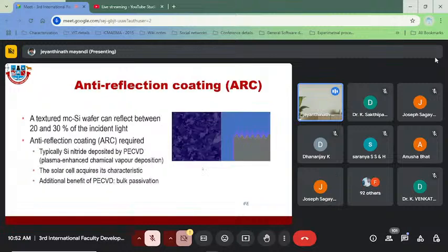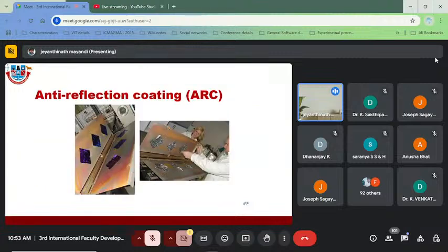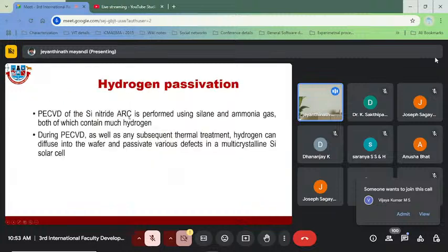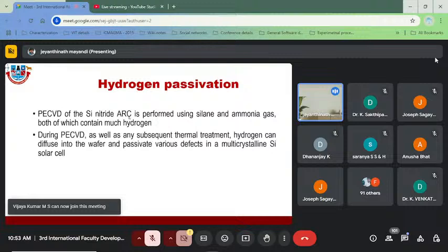Once the parasitic resistance is removed, you can make an anti-reflection coating on top of the textures, and this could increase the incident light entering the wafer by almost 30%. This is done by plasma enhanced CVD. This is a custom designed plasma enhanced CVD, and once the wafer is loaded, silicon nitride enriched with hydrogen is deposited. As I said earlier, this hydrogen passivates your surface, and the defects in multicrystalline solar cells will also be passivated.